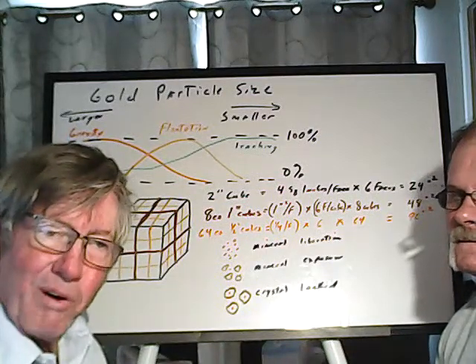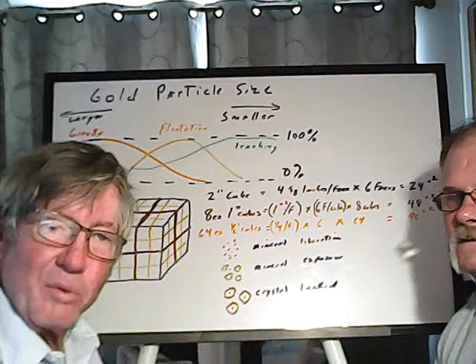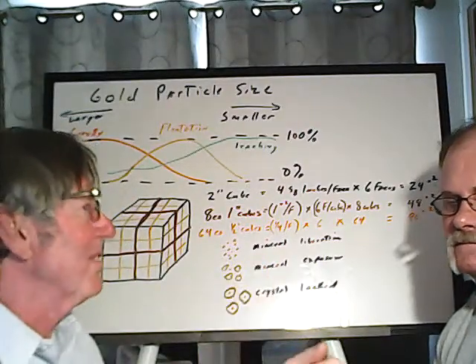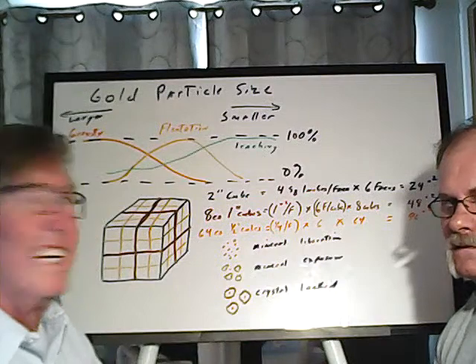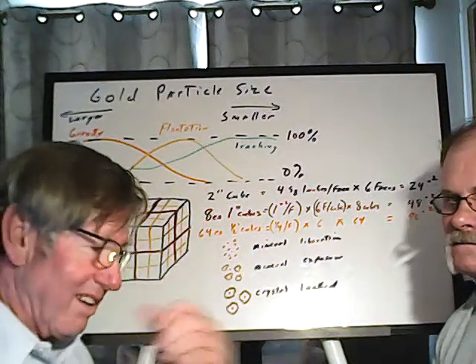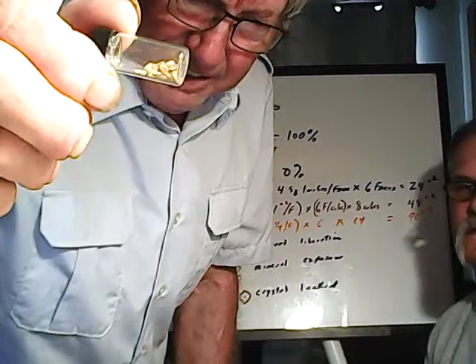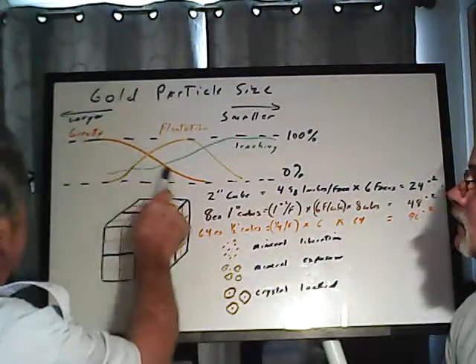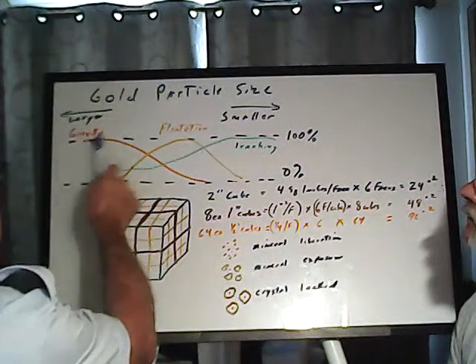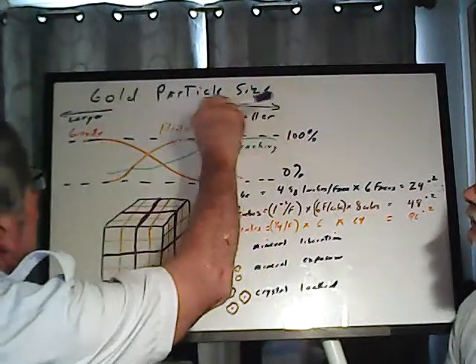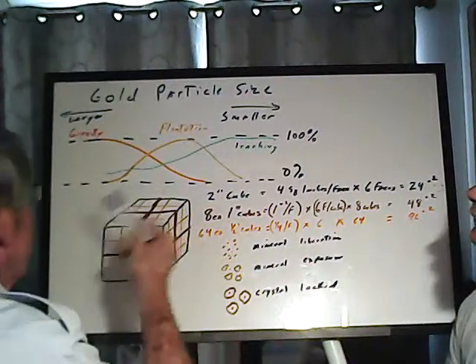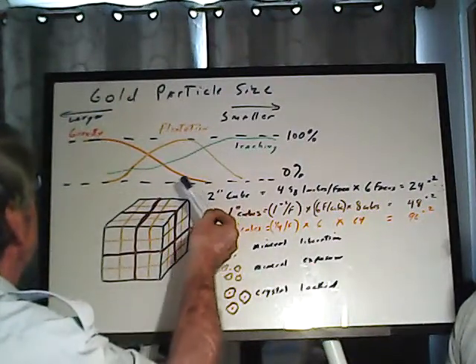The bigger the gold particle, the easier that is to work. Big nuggets are almost impossible to lose unless you reject them off the screen. Right. Anyway else, they're just going to sit and they're going to hang up and not move. So when you get gold this coarse, you should get 100% recovery in a gravity separation. And this is this kind of yellow curve here. The larger gold particles are here, the smaller are there. I didn't think, but I should have gotten some microfine gold for this, but oh well.